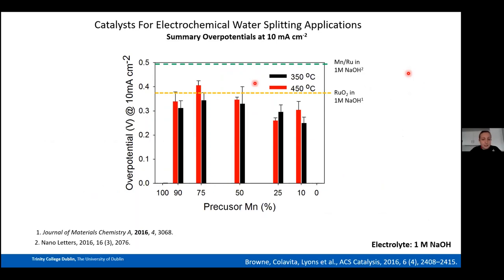A key conclusion from comparing our study to the previous literature is that lower Mn oxidation states, when mixed with ruthenium, do promote better OER catalysis. I also mentioned that during my first postdoc with Paula Colavita we used X-ray absorption near-edge structure (XANES) spectroscopy at a synchrotron to probe the Mn edge of our OER catalysts, which provides detailed information on the electronic structure of the targeted atom.